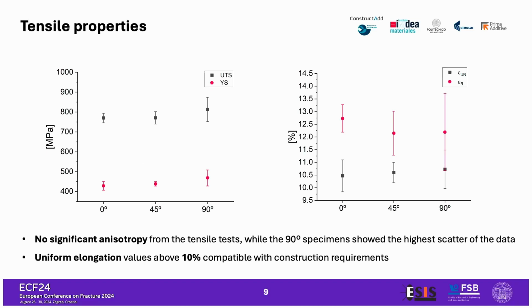Surprisingly, we did not assess any anisotropy in the material, because if you look at the values and consider the error bars, we can say that there is almost no anisotropy in the results. We obtained a yield strength between 430 and 470 megapascal and an ultimate tensile strength between 770 and 810 megapascal, while the uniform elongation was higher than 10% and the elongation at fracture higher than 12%.